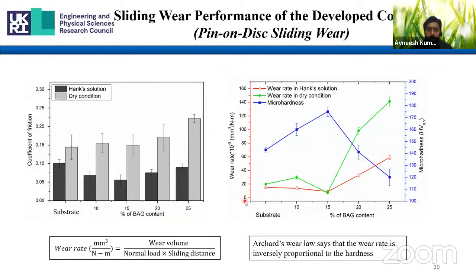Then while doing the sliding wear test, we monitored the wear volume, and using this equation we calculated the wear rate. These tests were done in dry condition and simulated body fluid condition. In dry condition, we have seen that only one coating was able to protect the substrate, that is the titanium 15% baghdadite coating. However, the hardness of this coating is higher than the substrate, and as Archard's wear law says, the wear rate is inversely proportional to the hardness of the coating surface. However, still the substrate was having better wear resistance than this.